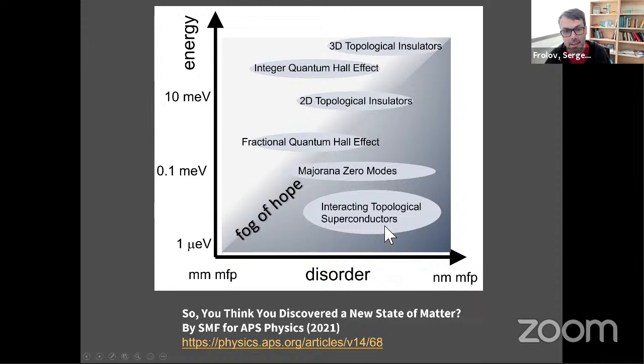And then something very delicate like interaction-driven phase like parafermions or something like that, SYK model is just such a small energy scale. And also complicated devices, which means a lot of disorder. That is just no chance that you can see it at the moment with present technology. No chance. And Majorana is kind of on the boundary, and fractional quantum Hall effect is dipping here because of all this. Anyon experiments are still inconclusive. It's on the boundary. So its energy scale is about the superconducting gap, which is a fraction of a millivolt, and disorder is hundreds of nanometer scale, mean free path or so in the best devices. And it's a long cloud in terms of disorder.